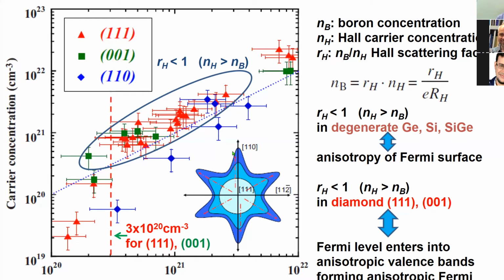The Fermi surface is in K-space. This surface is two-dimensional, but the real thing is three-dimensional. In these regions the holes are very heavy, and in these regions they are a little bit light. Anyway, this anisotropic effect shows very interesting phenomena.